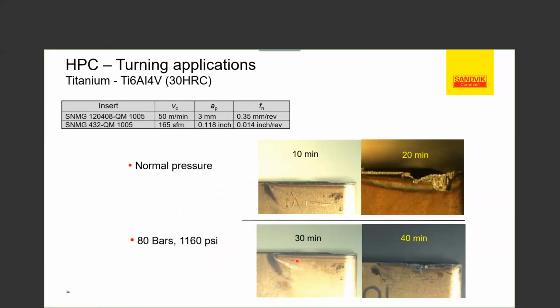And you can see here with an example too, utilizing the normal pressure and then increasing to about 80 bar, about 1100 PSI. You can see the difference in tool life here. You got that heat that's built up in the cutting zone. That pressure is helping bend the chip essentially back off the insert slightly and cooling down that zone. So you can see your normal pressure after 10 minutes, after 20 minutes, you can see a tremendous amount of notch, a lot of thermal activity in here. And then you can see here, same insert, same cutting parameters. All we've done is increase our pressure. You can see here up to about 40 minutes of tool life we've gotten, and we're just starting to see a notch build up. And the only thing we've done here is change the coolant pressure.